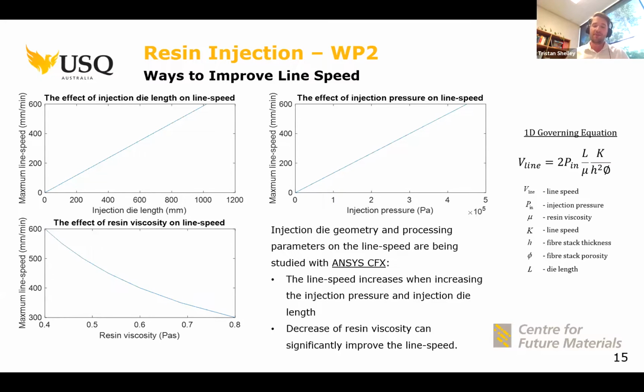Injection pressure. So you can see on the governing equation on the right hand side, an increase in pressure leads to an increase in line speed. But that's not to say that the increase in the pressure of the resin can not affect other parameters, as I mentioned before, such as deviating or causing a defect in the fiber stack. And another option, again, is to reduce the viscosity of the resin.